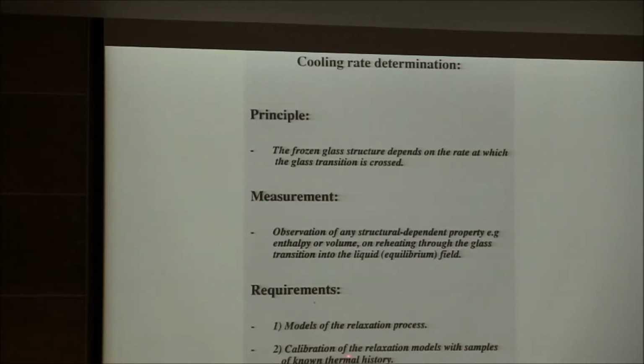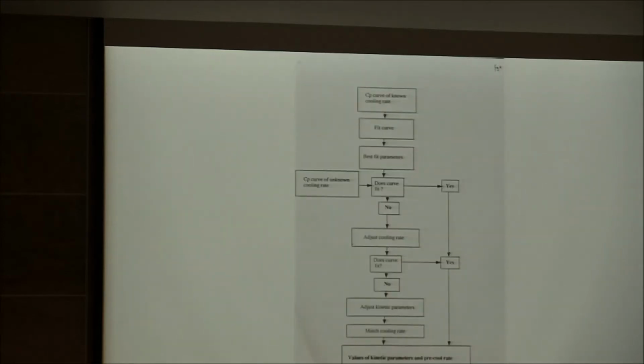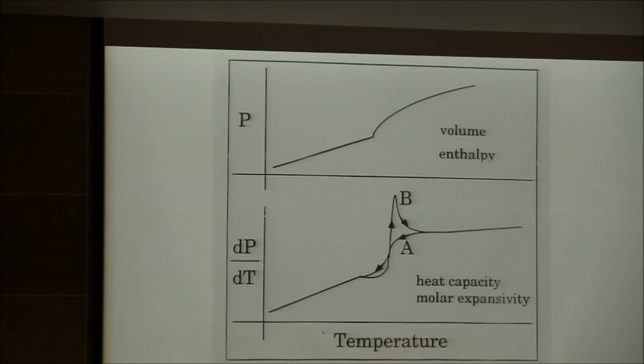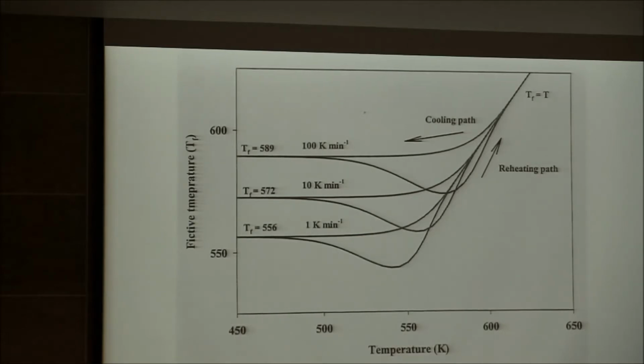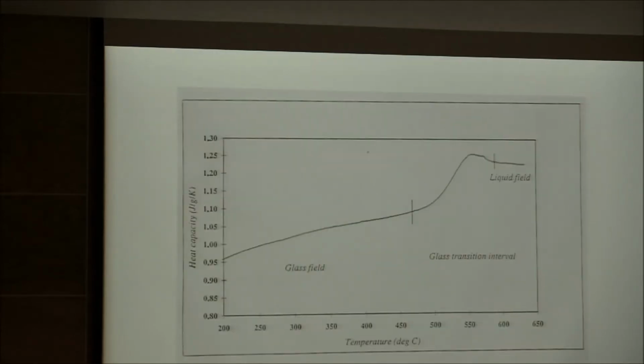We need to be able to calibrate how well we can do these determinations. Otherwise, it's just a nice idea. This is a terrible flow diagram which shows you the calibration. This is to drive home the point that if I have one single liquid here and I cool it at different rates, here are the rates, 100 degrees per minute, 10 degrees per minute, and 1 degree per minute, it will lock in a different temperature value of freezing, a different so-called fictive temperature as a function of rate. This is just another way of describing this dependence.